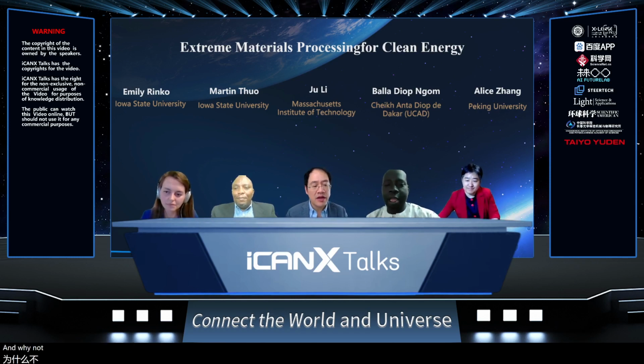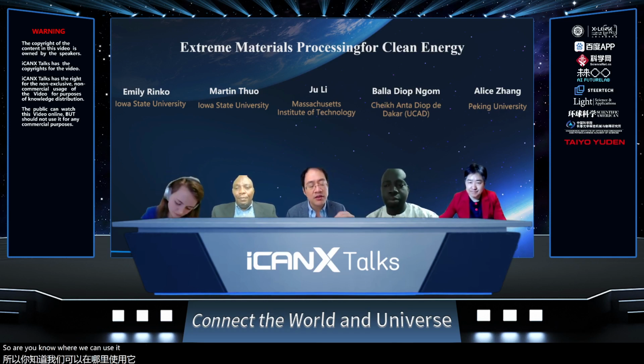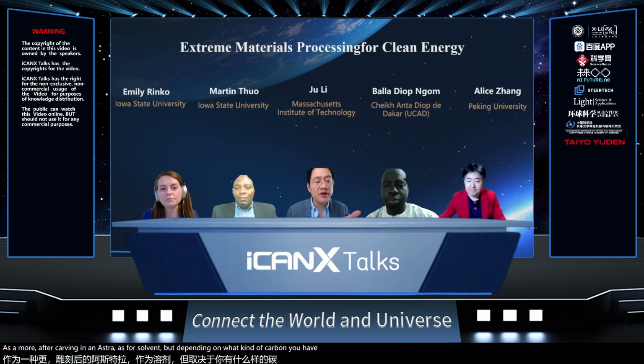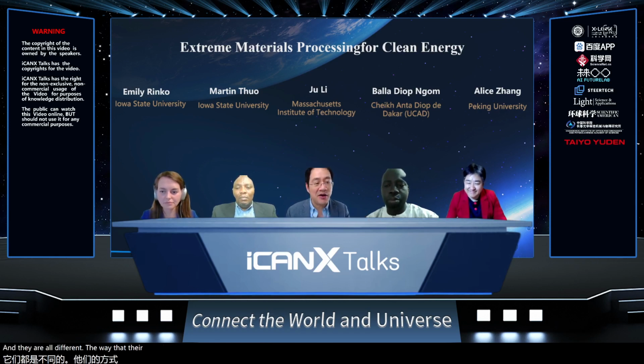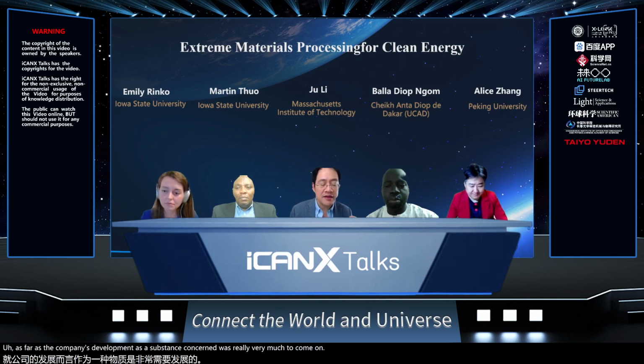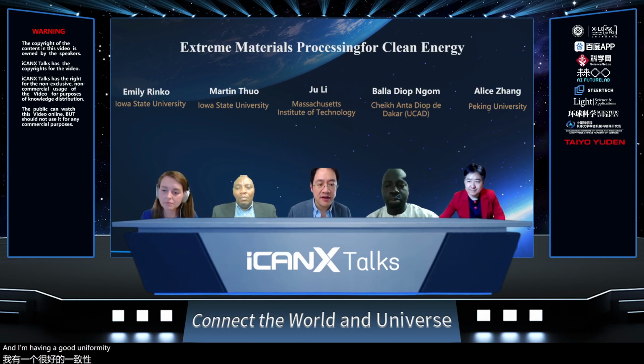One last thing I want to mention is that in this automated catalyst exploration, we also found that the wetting angle is very important. We can use water or ethanol as the solvent, but depending on what kind of carbon you have, the activity is different. We got carbon paper from different suppliers, and they are all different. Even from one supplier, we found that the wetting in different regions of the carbon paper is quite different. So as far as catalyst development is concerned, it very much depends on the processing history of the carbonaceous paper, and having good uniformity is key for getting consistent results.